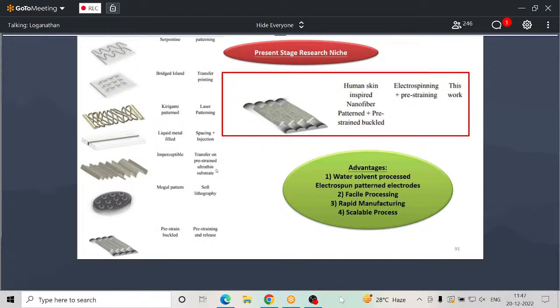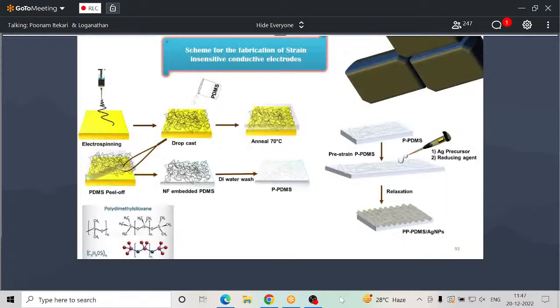And now, I want to say the present stage research niche, because in the past they have utilized all these kinds of structures. Now I want to use nanofiber based nano microstructures to fabricate. Why do we want this kind of structure? Because these structures are water solvent processed, with facile processing and rapid manufacture. You can easily and quickly prepare them, and then it's scalable. So this is the method we adapt. This is the schematic. You can see how we start with electrospinning, and we use some conventional stretchable polymers like PDMS, polydimethylsiloxane, and then we anneal them, and then we etch them, and we end up with these micro nanostructures with some conductive silver nanoparticles on them. We form them by in situ methods.